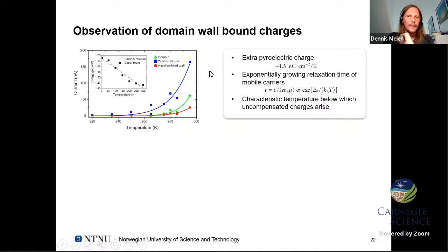But when you think about it, it's quite interesting, because the colder the material is, the more difficult it will be to bring the carriers to screen the polarization charges. Because if I cool down a ferroelectric, the polarization will still grow. And in our case, it's about 1.5 nanocoulomb per centimeter squared. So we need to screen the increasing bound charges at the walls. At the same time, the relaxation time for the carriers goes up, so we will have really a problem at low temperature to screen the walls.